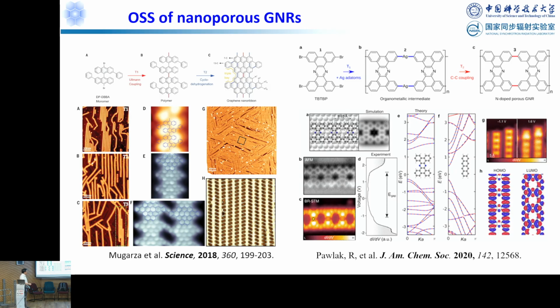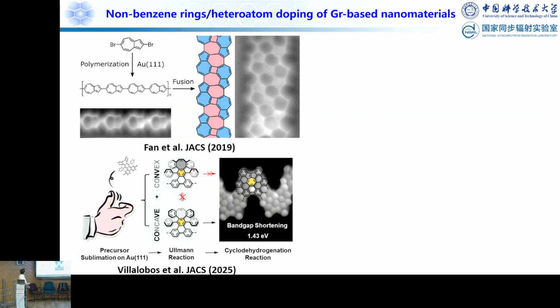You can really tune the structure, and then there is this work on non-benzene rings. For example, this is from another group. They use these 5-7 precursors, and first the Ullmann coupling forms the ribbon, and then with further temperature increase the lateral fusion happens, and forms a nanoribbon with only non-benzene rings. And here Carlos did very beautiful work also, with 5-7 rings. You can see, I didn't show it, but the band gap is only 1.43 eV.